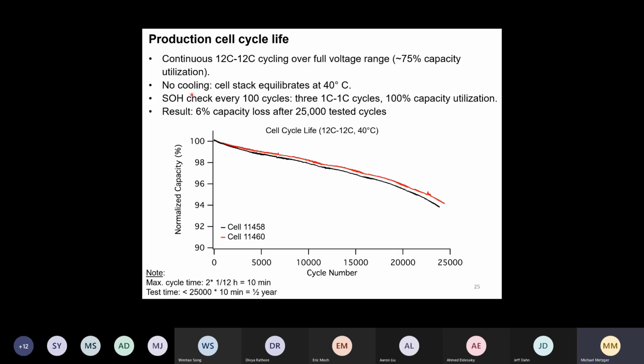And you have then only 6% capacity fade. So it goes from a normalized capacity of 100 to about 94 in 25,000 cycles. And these are 2 cells shown here. So that's quite incredible cycle life.